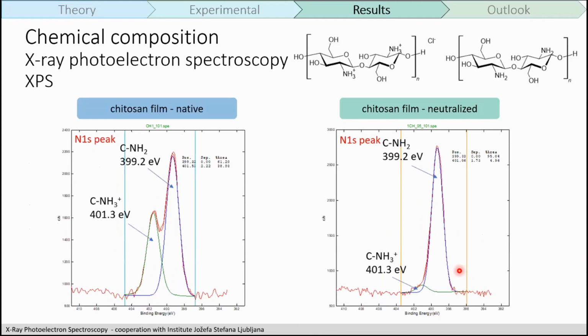However, we did find that in the nitrogen peaks, the protonated nitrogen area dropped from approximately 40% down to 4% after neutralization, which confirmed that the neutralization step of our surface actually worked.